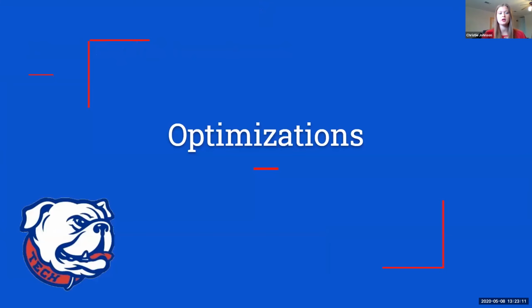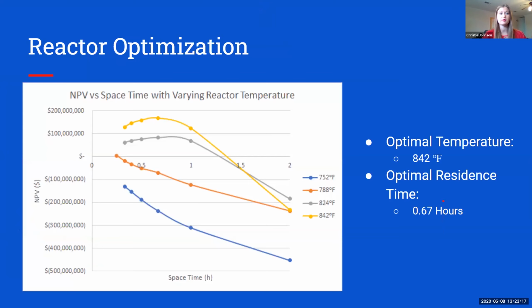So now I'm going to go a little bit more into some of the optimizations that were completed on our system. The first and probably most important was the reactor optimization, because if we weren't operating at the correct space time and temperature, then we wouldn't be maximizing our profit from converting to our products. And so you can see from the graph here that we were able to find an optimum at a temperature of around 842 degrees Fahrenheit and a residence time of 0.67 hours, or around 40 minutes.